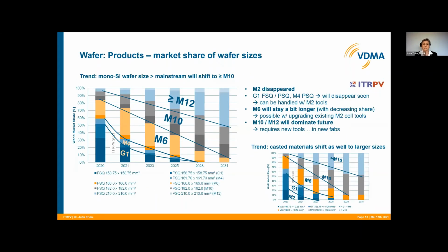This is clearly shown in these diagrams, where we distinguish between the mono material and the crystalline or cast materials. Here you can see that the G1 and the M4, the smaller formats, will really disappear. At the moment, the biggest share is M6. But in the next years, between M10 and M12, the share will be more or less half-half. And similarly for the cast materials. The smaller M6 could stay a little bit longer because this is possible by upgrading the older M2 cell tools. But if one would like to go to M10 or M12, we really need new tools and new fabs for this size.